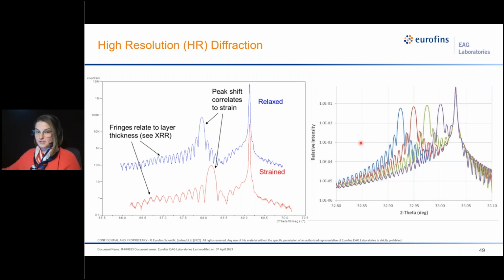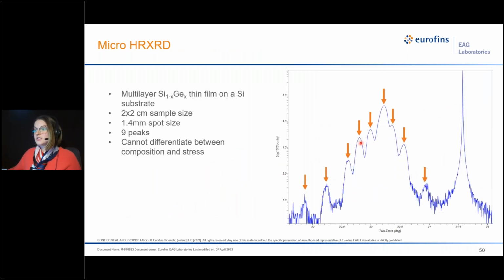This is a symmetrical reflection. Now, in order to deconvolute the peak shift in a symmetrical reflection, you have to move to an asymmetrical reflection and do the reciprocal space map collection. So we're going to use a multi-layer silicon germanium thin film for the example. This has 9 peaks plus your substrate peak, and this was about a 1.4 millimeter spot size. Again, we don't know why these peaks are shifting.